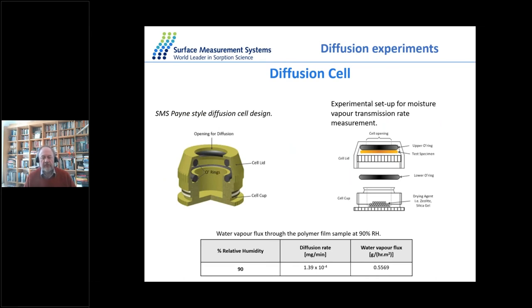The other thing we can do is, that's when diffusion is, if you like, two-sided. There are some cases where we don't want to do the experiment that way. We actually want to measure it in a slightly different fashion. And this is effectively a single-sided diffusion experiment. This is a slightly more accurate measurement in my experience. What we're going to do is take a small piece of polymer film and trap it between two O-rings here.